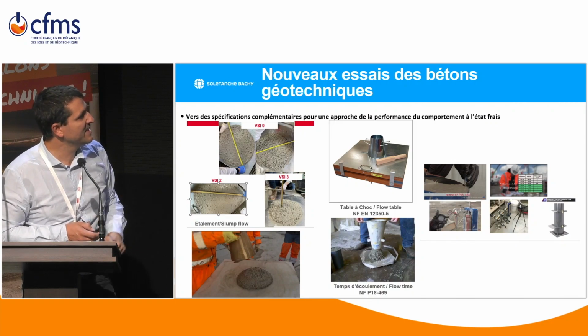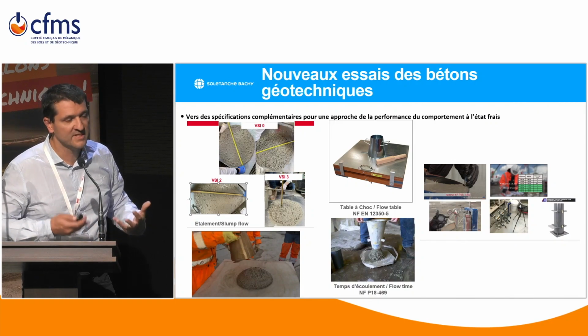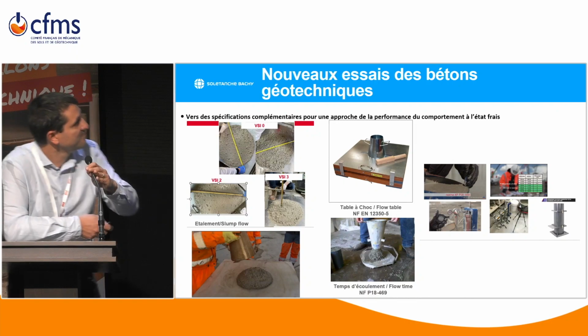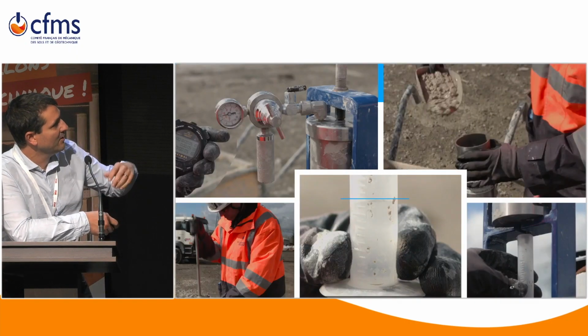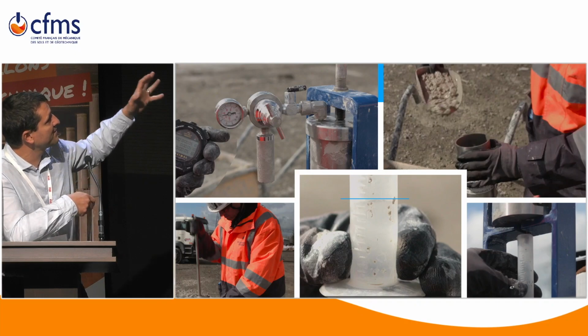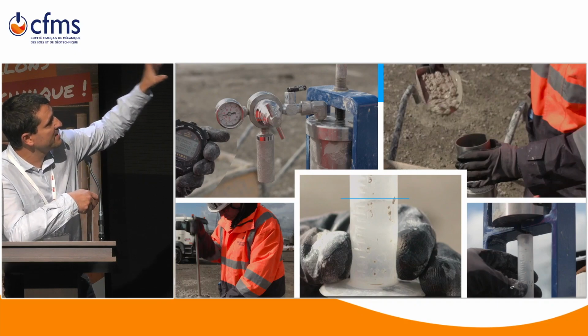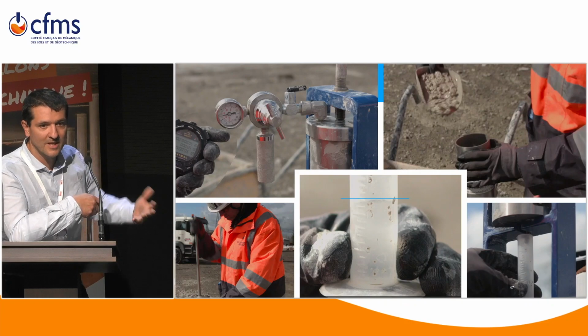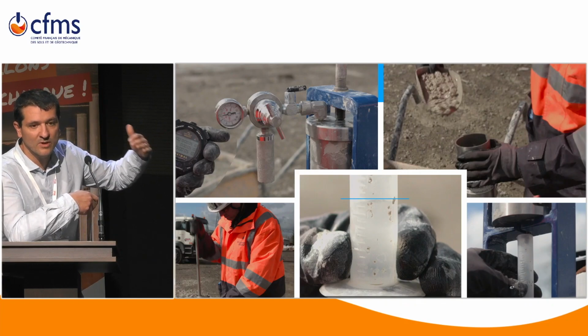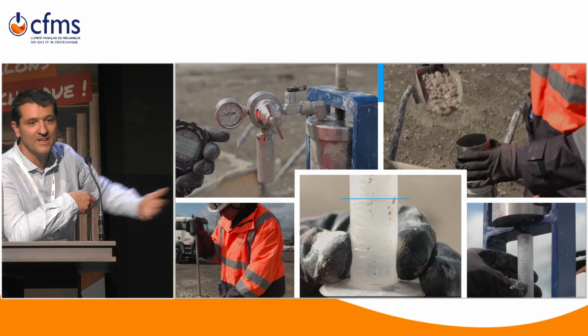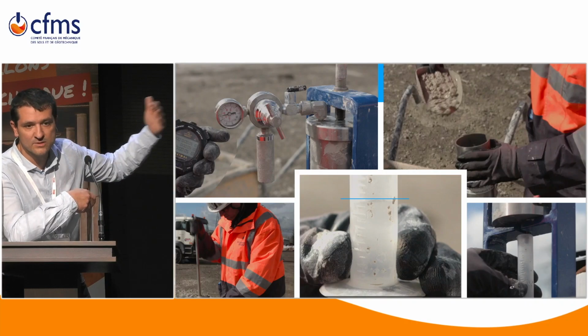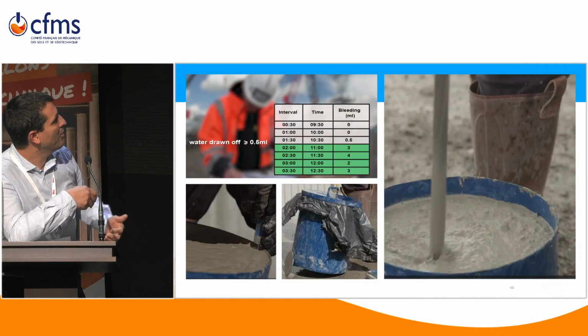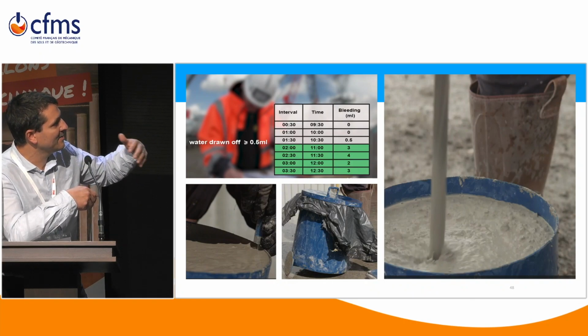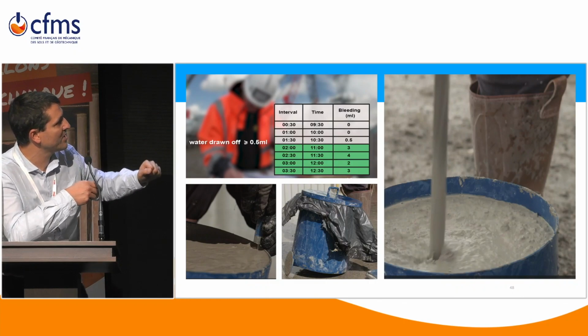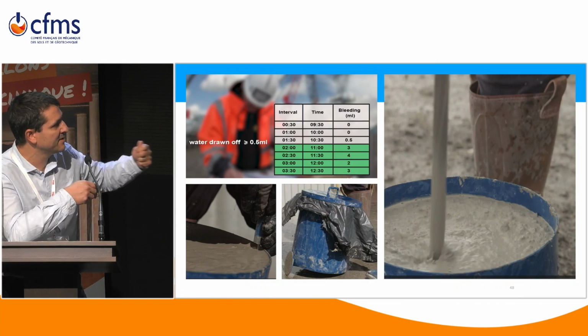Stability test, bleeding test, that helps you to measure the ability of concrete to retain its water. So in more detail, for stability, we have a suite of tests. It's a very simple cell that we put into pressure, and we have a threshold value of the maximum water that should be let out. It's a very simple test that lasts 5 minutes. Another test has a duration a little bit longer because it's at atmospheric pressure, but very interesting to identify the potential for